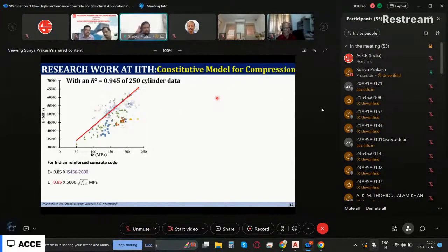Then what we did from our test, we collected all the data from all the existing literature, and then we came up with an expression for an elastic modulus. Just like in IS code, we have 5,000 square root of FCK. Instead of that, we said, okay, elastic modulus can be calculated from 0.85 times 5,000 into square root of FCM, where FCM is your cylinder strength.